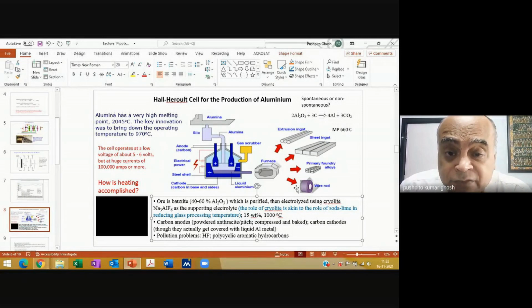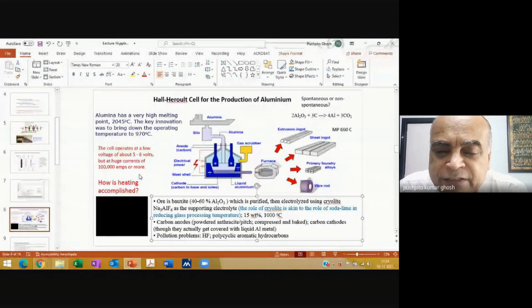Now, because the cell resistance is quite high, especially because although we say cryolite is an electrolyte, it's not a great electrolyte. So it offers considerable cell resistance. So with such a high cell resistance plus the very high current, my I squared R term is extremely high. So high that I can actually heat up my cell to this temperature. And so the heating of the cell to the temperature is a natural consequence of the I squared R or the ohmic losses. So it's not as if the entire ohmic loss is a wasted effort. It's not. They have used it very intelligently.